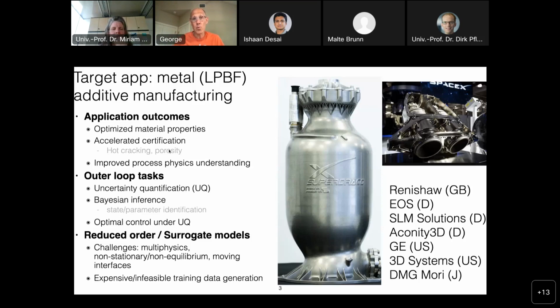It turns out there is quite a significant variability and interplay between the powder distribution, the material, the laser parameters, the machine, and how we decide to realize the shape, and that can create problems with respect to excessive porosity, cracking, and failures, and basically quality.